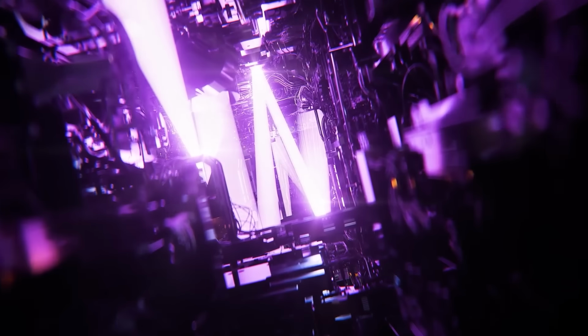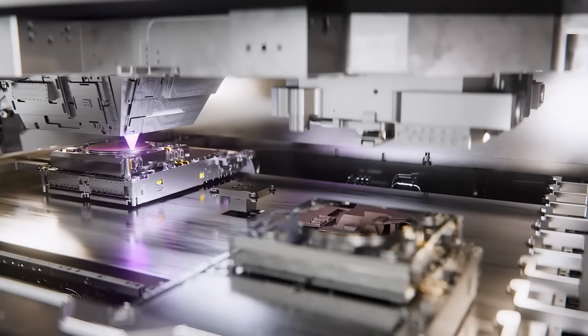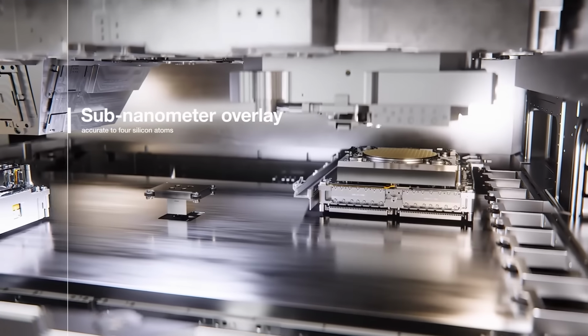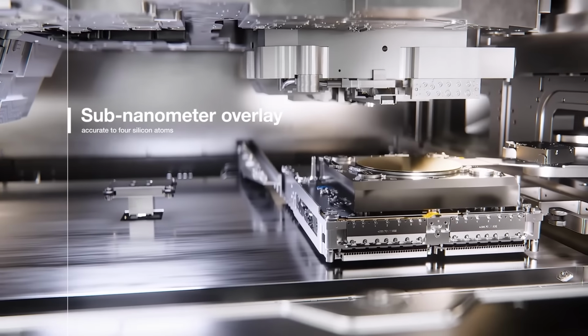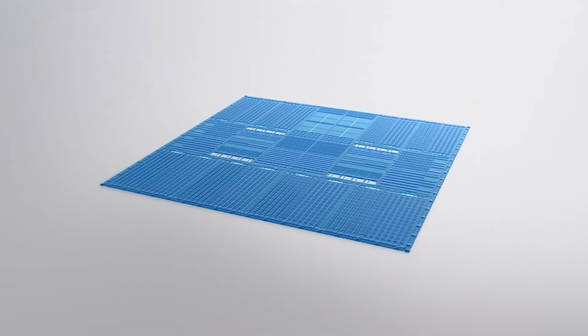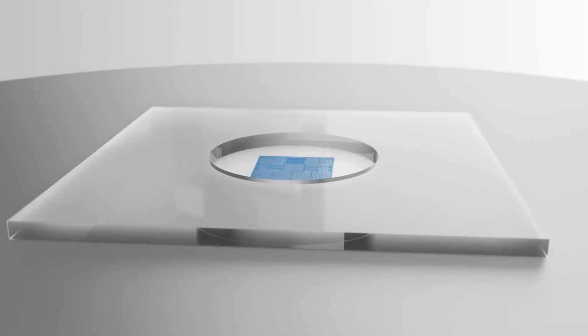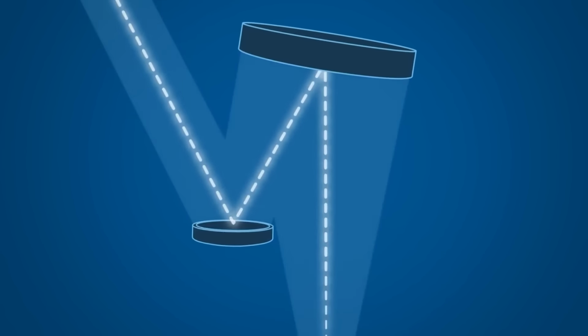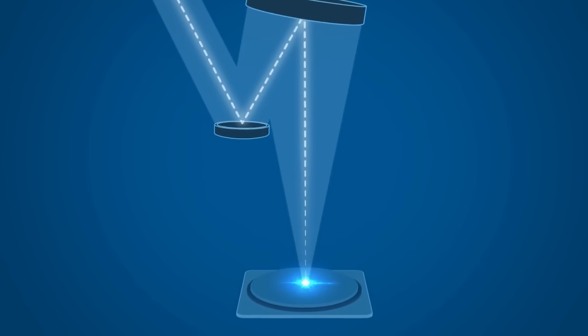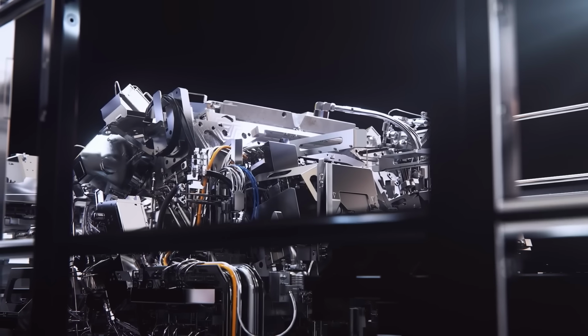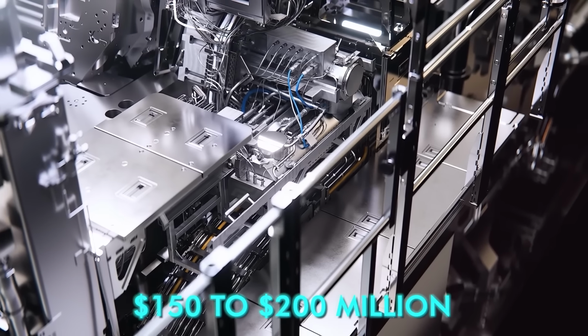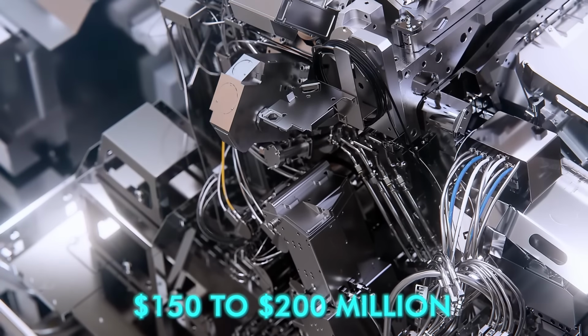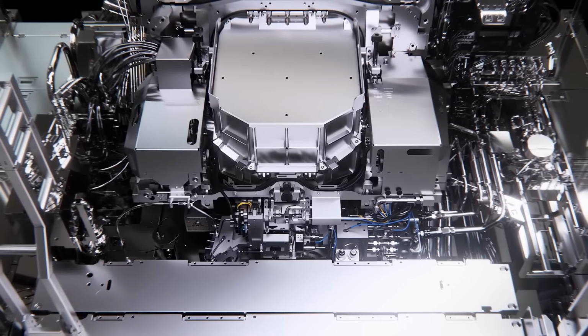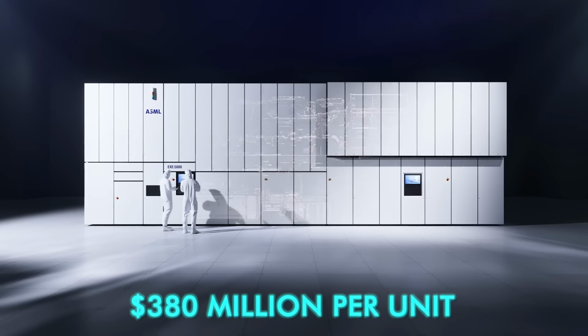The light is then collected by a curved mirror and bounced through a series of incredibly precise optics. Mirrors coated in alternating layers of silicon and molybdenum just a few atoms thick project it through a pattern mask and onto the wafer. EUV light is absorbed by almost everything, including air and glass, so the entire interior operates in a vacuum. No glass lenses, just mirrors. The most precisely polished mirrors ever manufactured. The standard EUV machine costs somewhere in the range of $150 to $200 million. The new High-NA version costs around $380 million per unit.